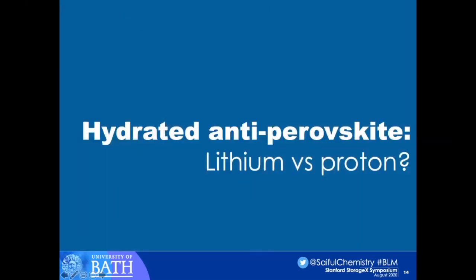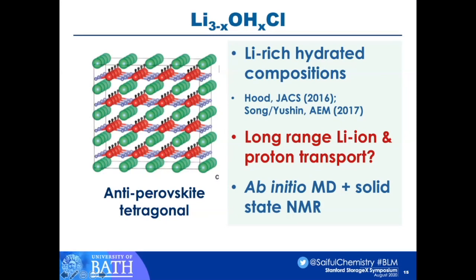We also extended this work on the anti-perovskites to the hydrated form. There was debate that they took up water very readily, and this is work of Hood, Song and Yushin, published in Advanced Energy Materials. Essentially, the OH groups are creating more lithium vacancies and can increase the lithium ion conductivity. But the debate really was whether there was any proton transport. This stems from the fact that, for those who've worked on proton conducting perovskites, as I have, there has been considerable work on proton transport in perovskites. But does it occur in these anti-perovskites?